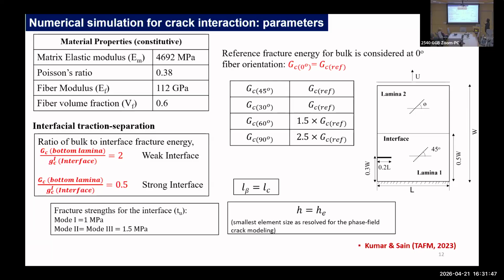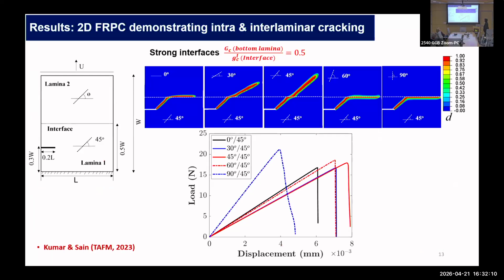And we did many different case studies. I will show you one particular one. And of course, these are the typical material properties. We studied two restrictive cases. One is when the interface is weaker than the bottom lamina toughness. Another is vice versa. Basically, the interface is stronger than the bottom lamina. So with that, let's look at some of the results that we saw. In this particular example, I'm showing you that the bottom lamina fiber orientation is kept at 45 degrees. And as I said before, the pre-notch is here. The interface is at the mid plane. And we keep on changing the orientation of the top fiber and pull this laminate under uniaxial tension.